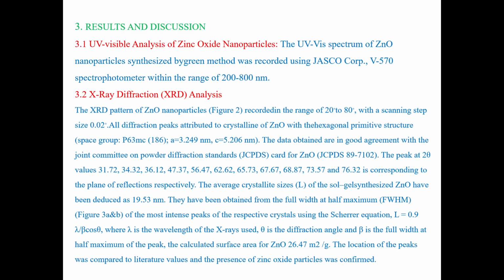The peaks at 2 theta values, that is 31.72, 34.32, 36.12, 47.37, 56.47, 62.62, 65.73, 67.67, 68.87, 73.57, and 76.32 correspond to the planes of reflection respectively.